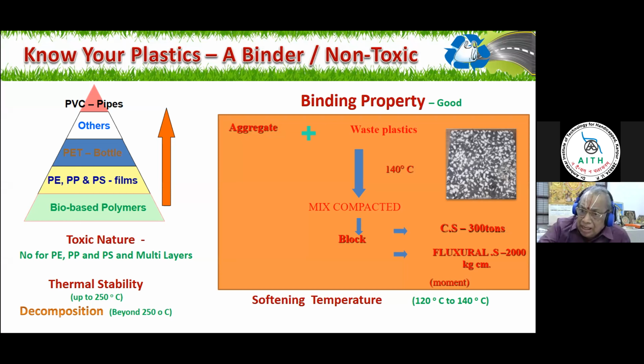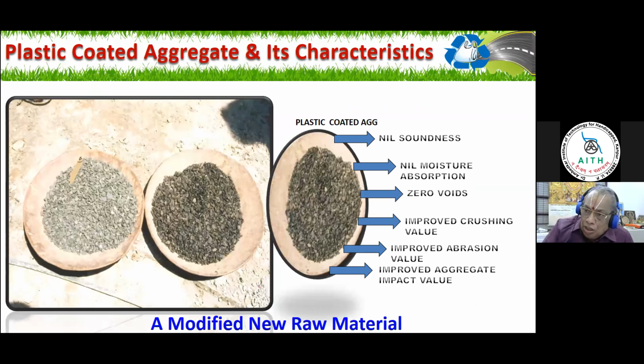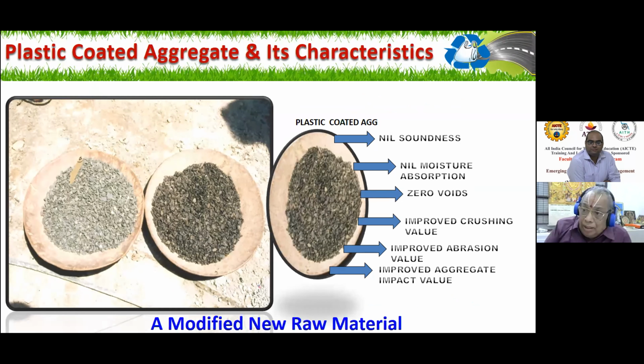This slide shows plastic has a great property called binder property. Now, the stone is taken, conventional stone or granite stone, and coated with the plastic. You can see the second slide is coated with the plastic. Once you coat with the plastic, the quality of the stone is improved. Nil soundness, nil moisture absorption, zero void, improved crushing value. So it improves the quality of the stone, the quality of the road also. Therefore, plastic not only helps as a binder, but also helps very much in this respect.